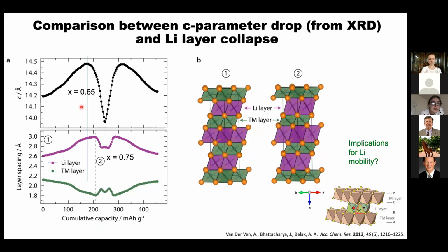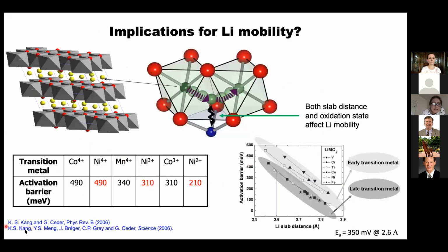So this is the c parameter collapse. Here's the layer structure, and you can break that down into the spacings in the lithium layers where the lithium ions move and the metal layers. When you do that, you can see that you carry on to about 200 milliamp hours per gram, and then you get this collapse at about x equals 0.75. Let's think about this in terms of the implications for mobility. This is work of Gerbrand Ceder and Kisuk Kang and myself a number of years ago, where we thought about how lithium ions move in the materials. Basically, as the layers collapse, you get a short repulsion between the lithiums in the layers. So in order to hop, you've got to go octahedral site, tetrahedral site, octahedral site.